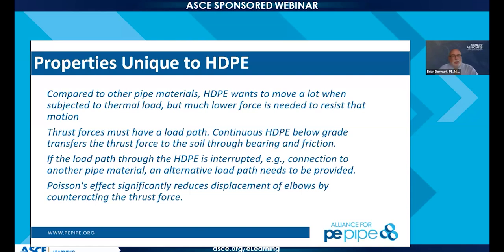Yeah, just to add to that a little bit, the thermal changes on short-term installations, like say a trenchless installation, those you would use a higher modulus on. Whereas if your installation, say some pullbacks for directional drilling might take 30 to 40 hours, you'd use a slightly lower modulus. And this information is heavily discussed in the PPI manual, and most manufacturers can tell you how much the modulus can change. So use the charts and figure out your time factor.